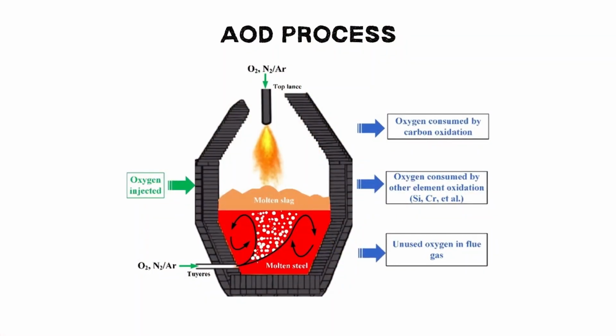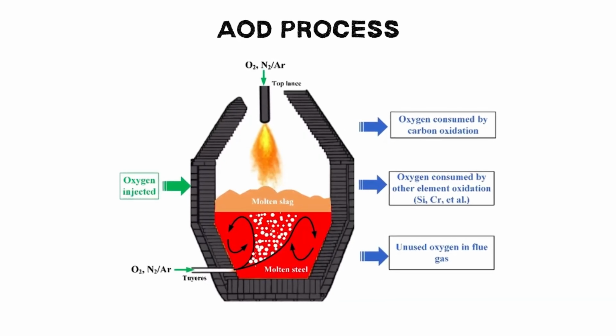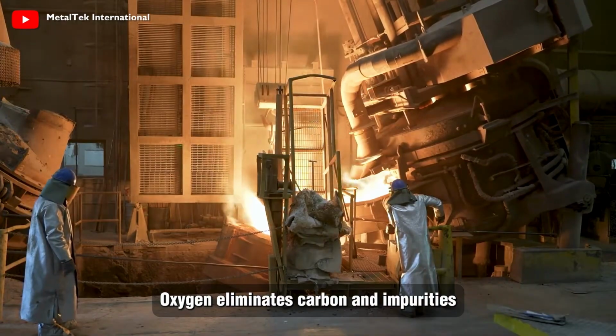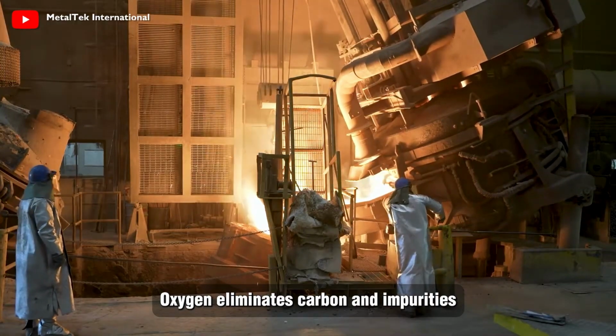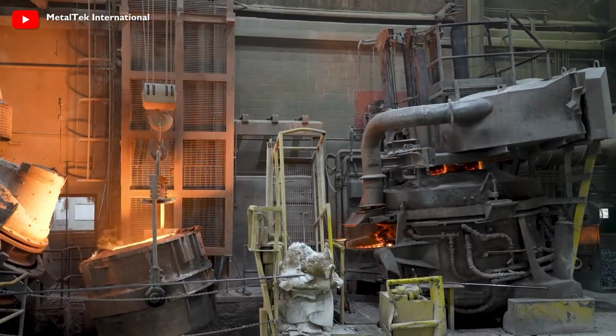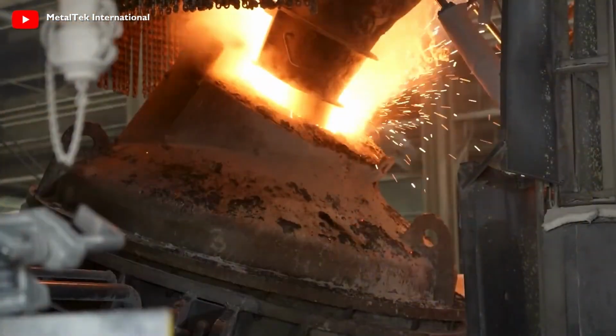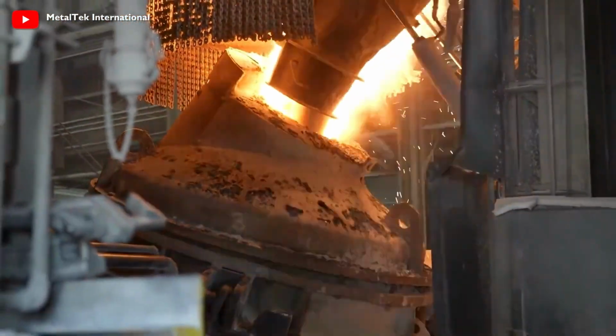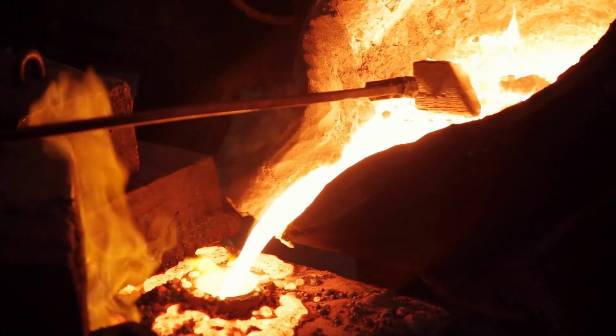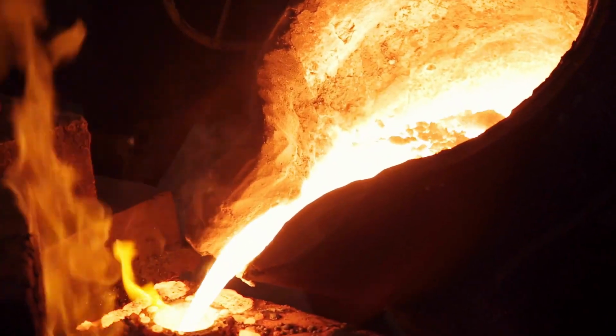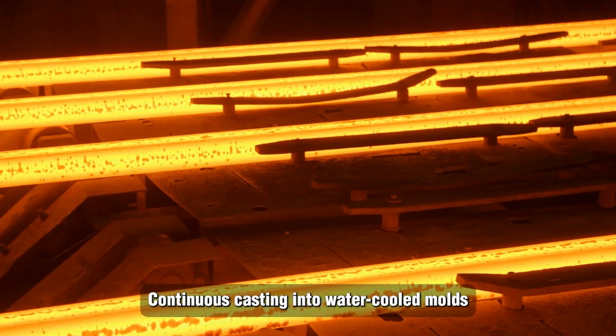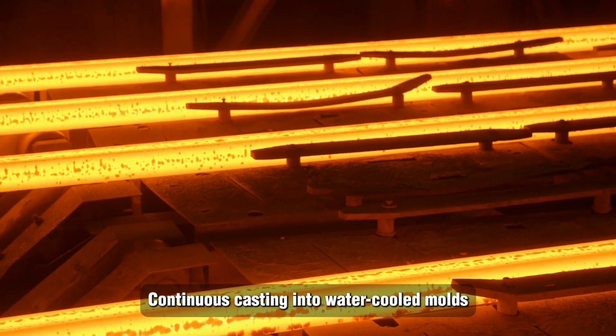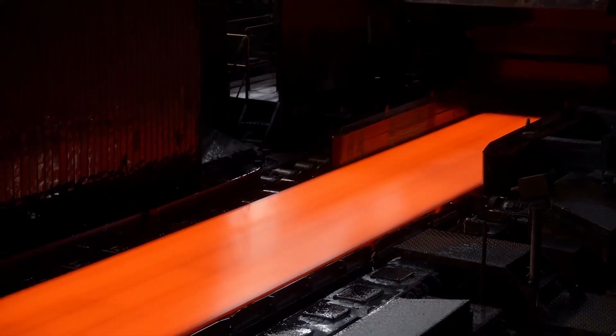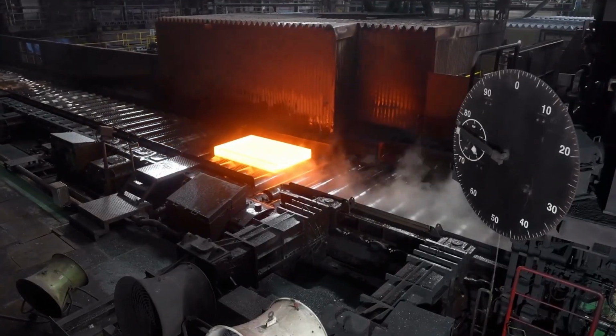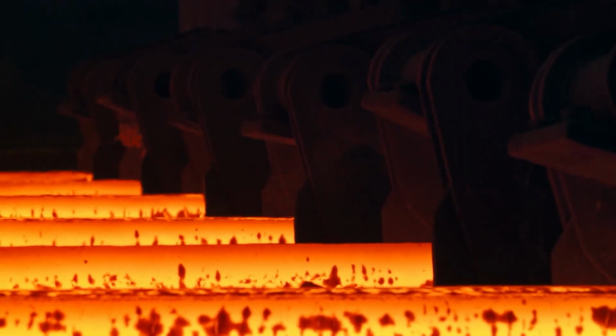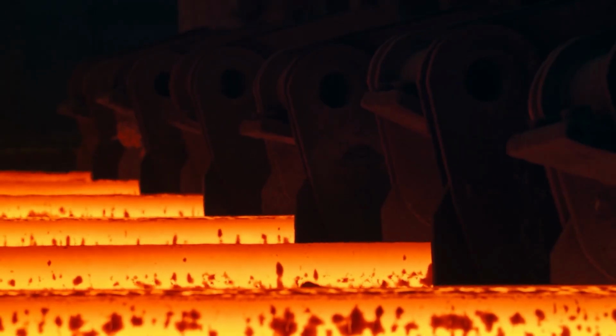Once all those alloying elements are blended into the molten iron, there's still work to do because impurities inevitably creep in during the process. That's where argon-oxygen decarburization, or AOD, comes in. During AOD, a mixture of argon and oxygen gets injected directly into the molten metal. The oxygen reacts with carbon and other impurities, forming gases that escape the mixture entirely, while the argon helps regulate temperature and prevents the chromium from oxidizing too aggressively. What comes out the other side is a precisely controlled, refined stainless steel, exactly matched to the properties it needs.